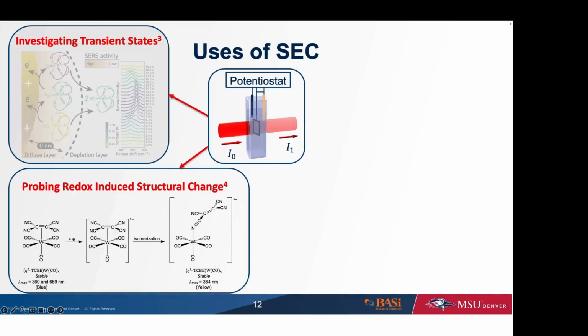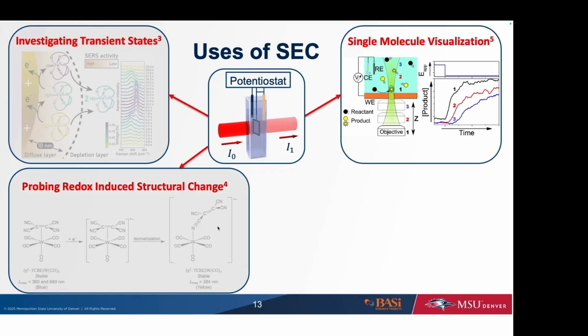They were able to see a transition from an eta-2 to an eta-1 coordination mode to this tungsten center. And they were able to watch this isomerization happen through the spectroelectrochemical technique, demonstrating that you can use SEC to probe redox-induced structural changes, as well as just transient states that are maybe not as stable. So this is a transition between two stable species, but the isomerization was difficult to capture by other means.